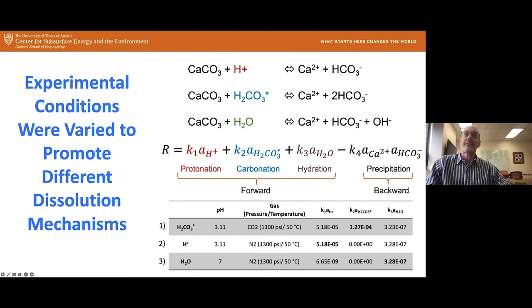These Ks are rate constants times the activity, or you could think of them as concentrations times an activity coefficient for each of these. So we set up three experiments, and we did these in replicate. In each experiment, we tailored the conditions so dissolution was controlled by carbonic acid, by protons, or by water. When it was controlled by carbonic acid, we had pressurized, supercritical CO2 in the system, which drove the pH down to 3.1. We matched that using a nitrogen atmosphere with HCl to get the same pH, and for the water-dominated dissolution, we just had a nitrogen atmosphere at neutral pH. When you look at the relative magnitude of these three terms, you can see how they vary in each experiment, so we get the right term to dominate.